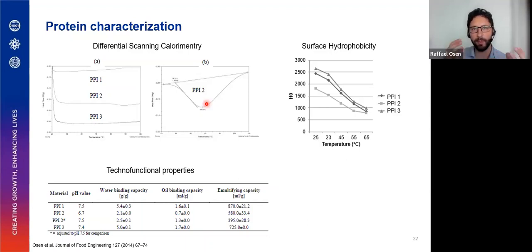And this can be explained by the folding of the protein, the structure of the protein. Usually for native proteins, the hydrophobic side chains are more trapped inside the molecule. During the denaturation process, the structure changes and partly unfolds, and then the hydrophobic side chains become available on the surface. The same thing can be seen here for the surface hydrophobicity: for protein number 2, we see the lowest surface hydrophobicity, which correlates very well with the denaturation. And as a result, looking at the technical functional properties, we can also see these effects for the water binding capacity, oil binding capacity, as well as emulsifying capacity, where protein number 2 has significantly lower values compared to the other proteins.